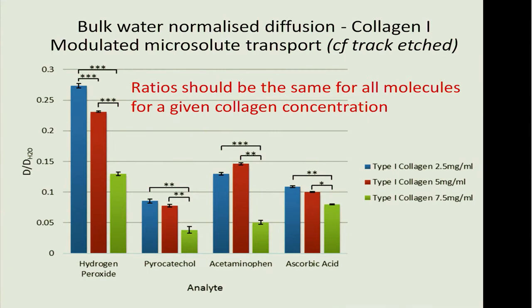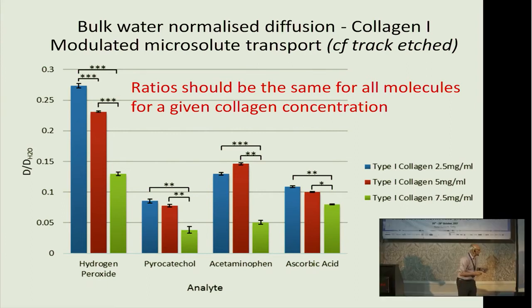But we came to yet another difficult, anomalous answer. Here's how it goes. These are ratios of diffusion through the materials, the collagens, and this is diffusion through bulk water, and the diffusion ratios, well, you don't expect that to be 1 anymore because you've got a barrier, fine. But so you're about 20% of what you should be. That's not the point. The point is that for each microsolute, the ratios against bulk water are different.